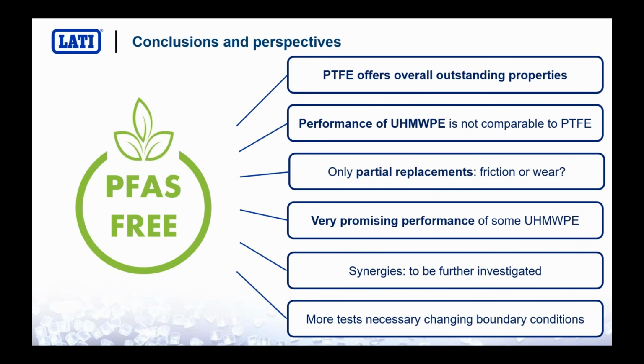For sure, more tests are necessary, because if we change the boundary conditions, if we change, for example, the load or the rotational speed, probably the results can also be different. That's the reason why these are comparable results, but at the end, tribological tests on the real part, on the real molded part with the real boundary conditions, are strongly recommended.